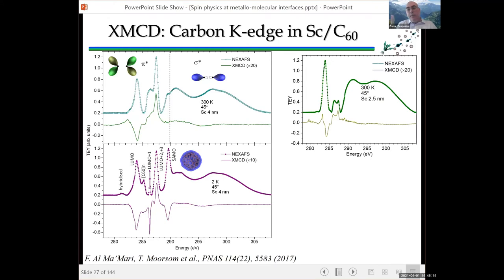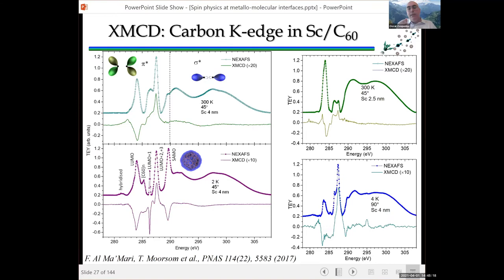And obviously this is an effect that is very sample to sample dependent and very dependent on temperature. So at low temperatures, you have more well-defined molecular orbitals that give rise to a slightly different dichroism structure to what you see at room temperature.